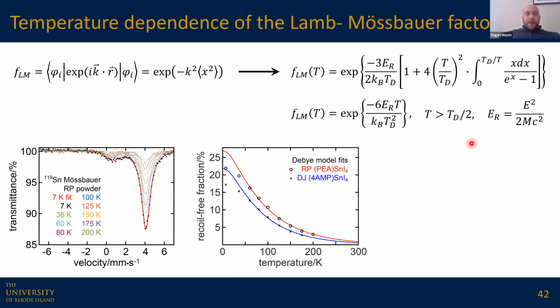But the primary temperature dependence that you see in Mossbauer spectroscopy comes through this Lamb-Mossbauer factor, which is basically saying what is the probability of a zero phonon nuclear excitation. And this just comes from the mean square displacement of the absorbers. And so we get this familiar Debye-Waller term here to give us this Lamb-Mossbauer factor that tells us how much our spectrum gets attenuated as temperature increases.